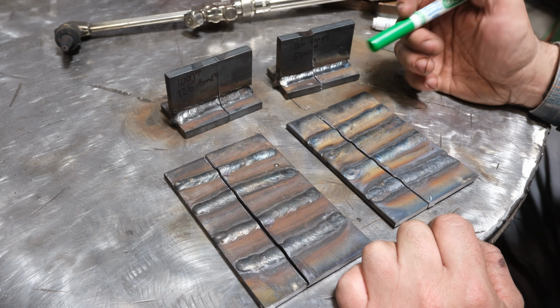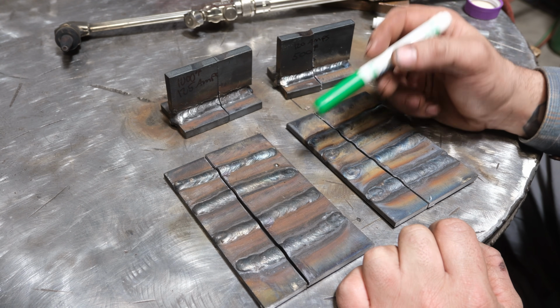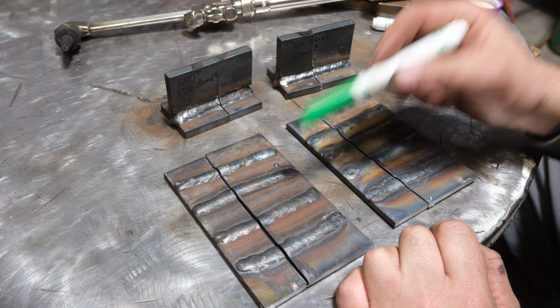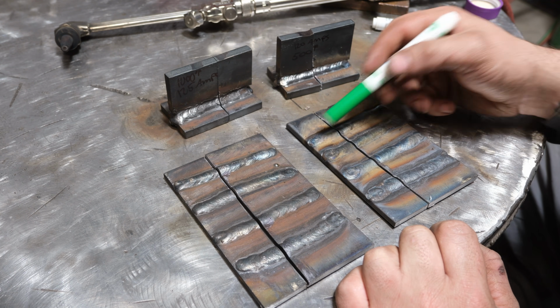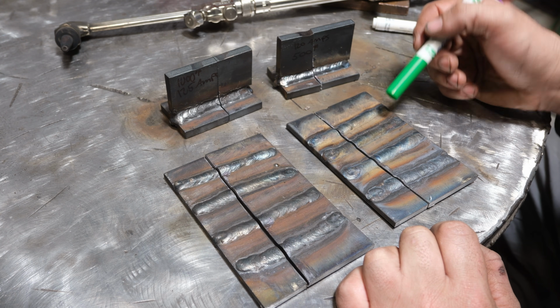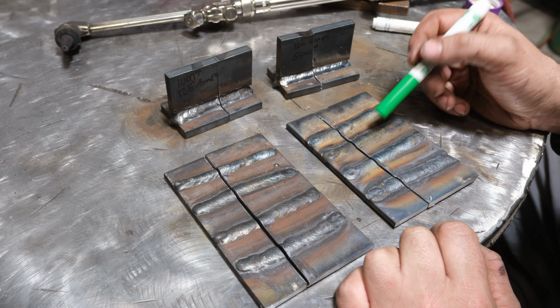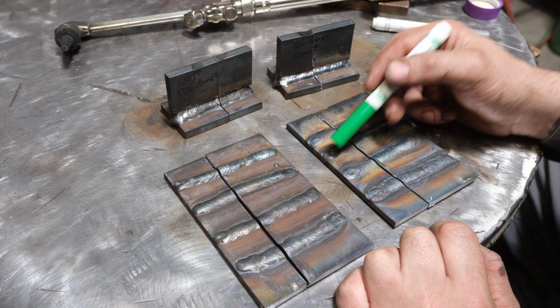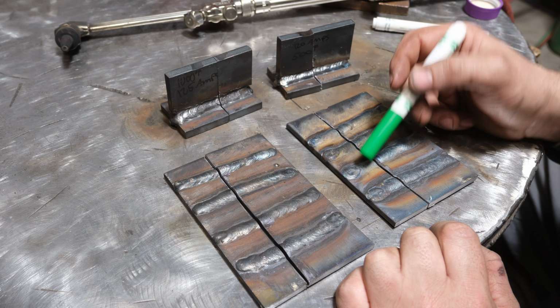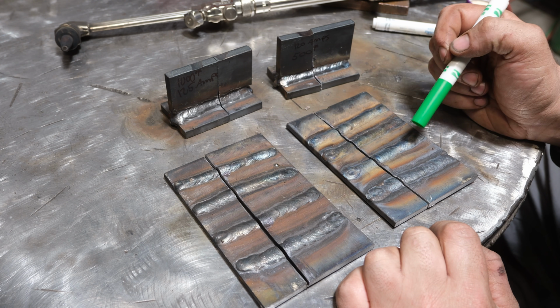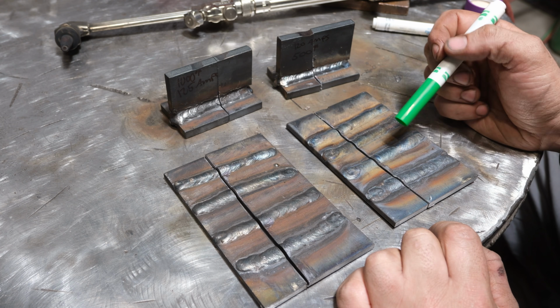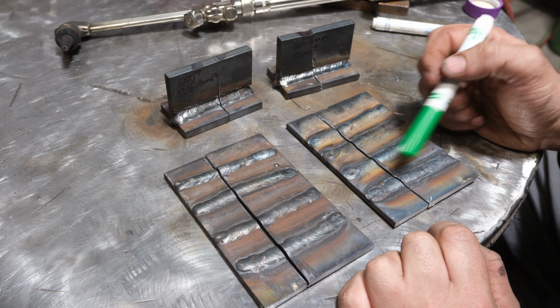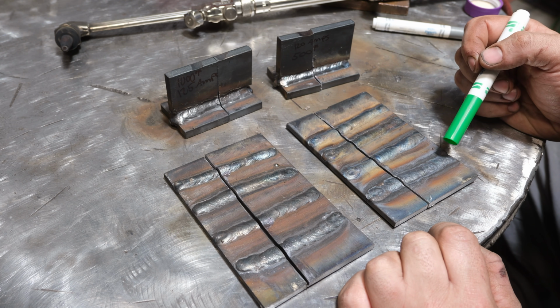So my apprentice Owen and I both did a test plate. I believe this is mine, this is his. And what we did is we did a weld on this cold, then we torch heated it to 500 in the area of the next weld, then we welded it immediately, then we torch heated it to 750, welded it immediately, and then torch heated it to 1,000 degrees and welded it immediately.